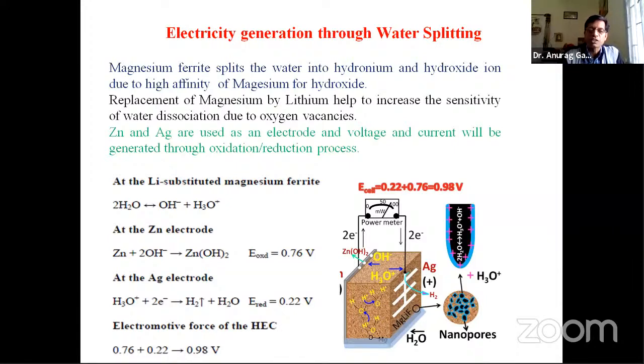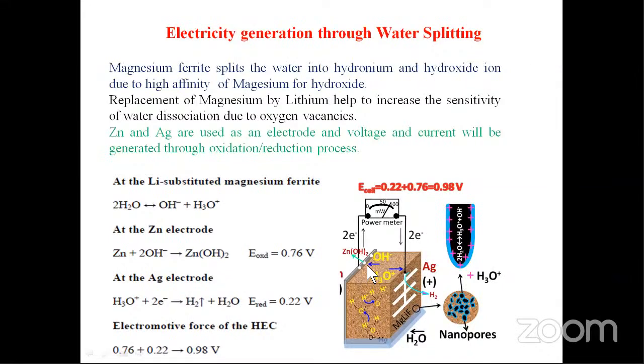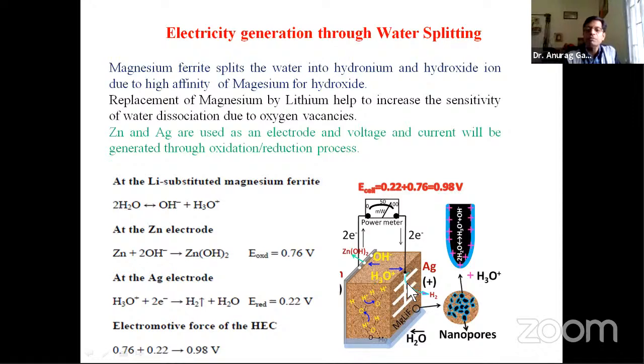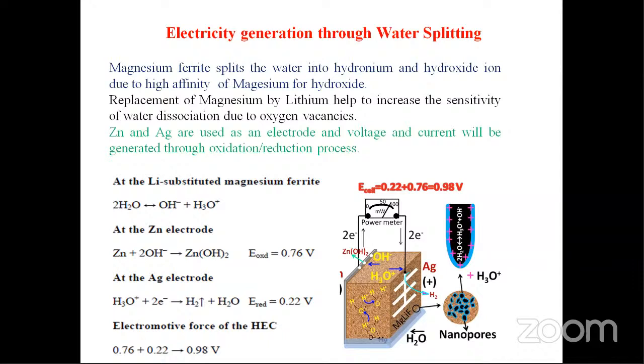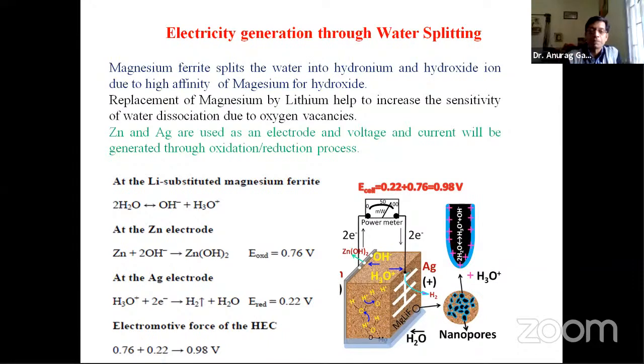Under the influence of this electric field, the splitting rate of the water is further accelerated and enhanced. So the water splits into OH minus ions and H3O plus ions. Then what we have with this material, this is our material side, and along with this, you can see that on one side we use the zinc electrode, and on the other side we have the silver electrode, or you could say we make finger-type silver contacts. So it's like a cell, a complete device. It has two electrodes, zinc on one side and silver on the other, and in between we put our material.